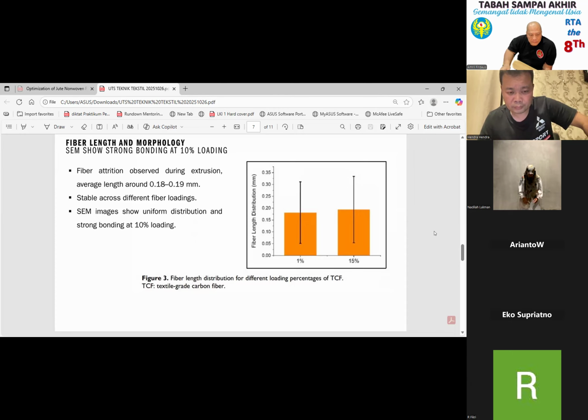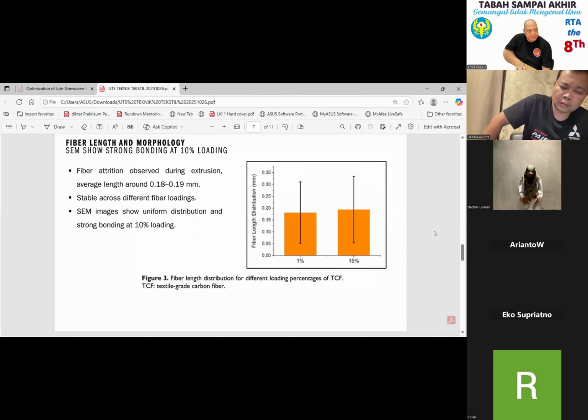In the study, after the processing, the researchers found the average fiber length was about 0.18 to 0.19 millimeters, quite short compared to the original one, which, remember, is 6.35 millimeters. Interestingly, once again, this fiber length remains fairly consistent across the fiber loading, from 1% to 15%. So the key takeaway is that increasing the fiber content didn't necessarily increase the fiber damage. The fibers were short, but their length distribution was quite stable.